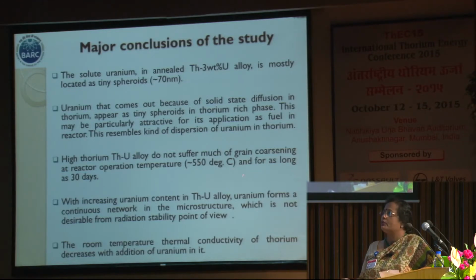That was not observed. With increasing uranium content in thorium uranium alloy, uranium forms a continuous network in the microstructure, which is not desirable from a radiation stability point of view. The room temperature thermal conductivity of thorium decreases with addition of uranium in it.